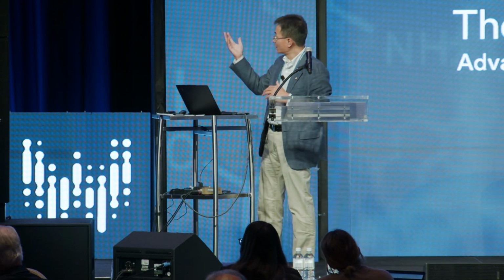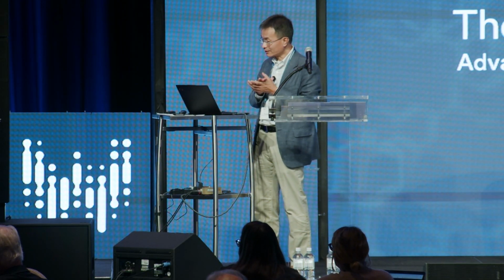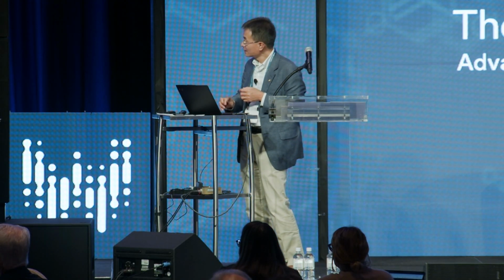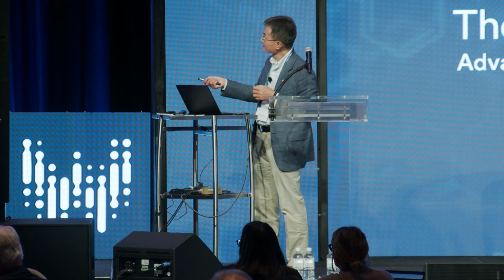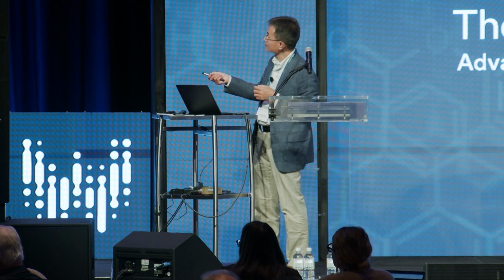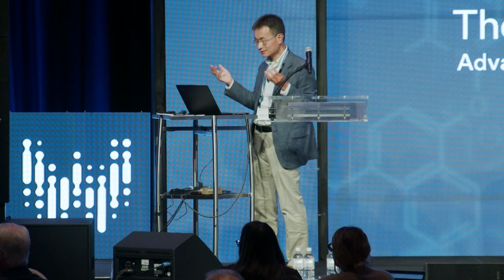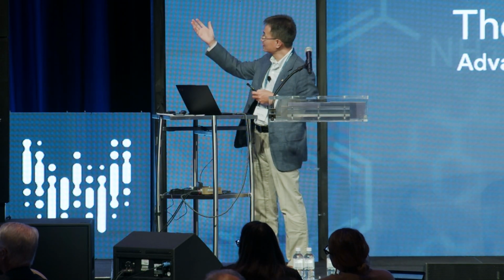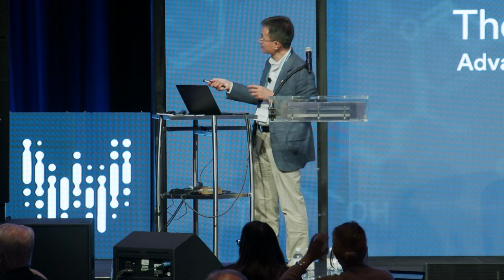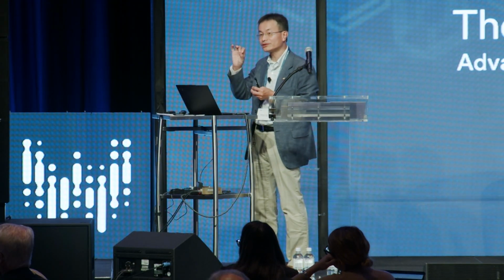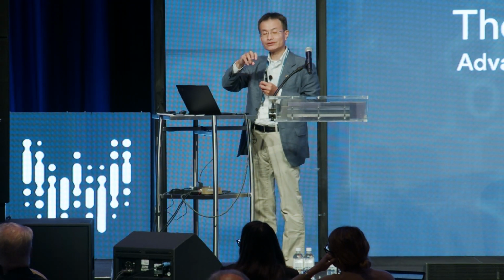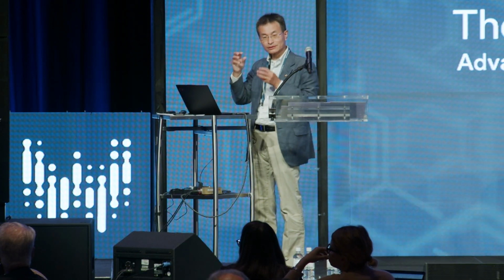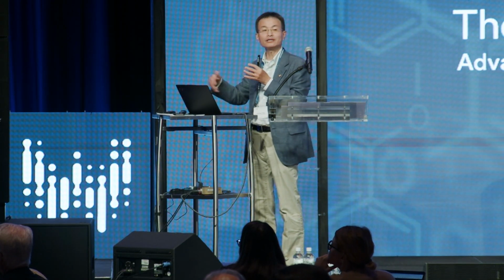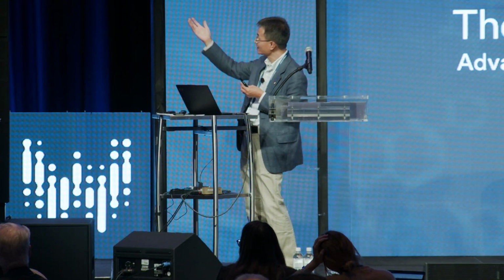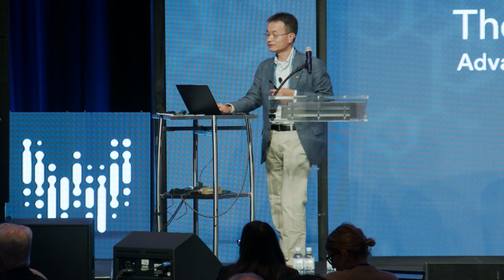Okay, why the nanowire photocathode or photoanode? Just two very quick reasons. One is the high surface area, and they can orthogonalize light absorption and charge migration, which the single crystalline channel gives you. The second is matching the solar flux with catalytic turnover. These are based on single nanowire photoelectrochemical measurements. You can measure how many electrons, under one-sun irradiation, you can extract to the surface to do chemistry, so that the electron flux can match the turnover frequency of the catalyst you put on the surface. The high surface area nanowires give you this advantage.